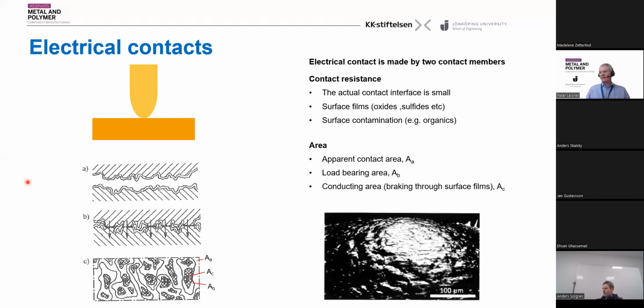So if we go into more detail and look at how it looks on the micro scale on the surface of the contact, it might look flat, but if you really zoom in, you will see something like what you see here. It will be micro rough, and you will have something on the surface. If it's non-precious metals, you have an oxide film, and even on precious metals like gold, you will have some surface contamination from the surroundings. So when you press it together, as you see in B, then you start to have the mechanical contact. It will be pressed, and you will have islands, which will be the load carrying area.